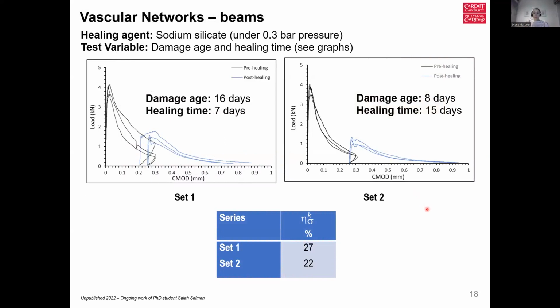So we have also considered sodium silicate in the vascular network. We had 4 channels in beams, sodium silicate under 0.3 bar pressure, and we wanted to look at the influence of damage age and healing time on the healing response. We can see that the results really aren't that dissimilar, and it does demonstrate that, despite the age of first damage, providing healing times for sodium silicate in excess of 7 days is not necessarily beneficial, and this is probably due to the exhaustion of available calcium hydroxide on the surface of the crack.